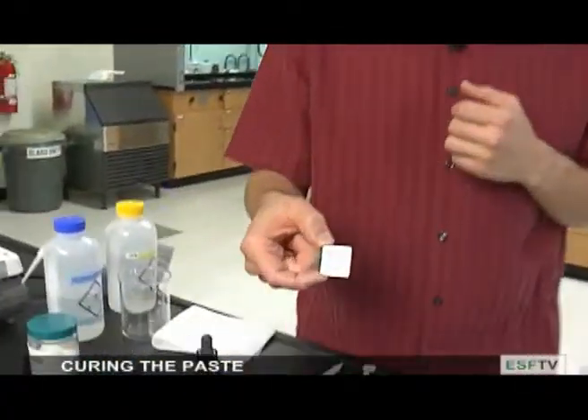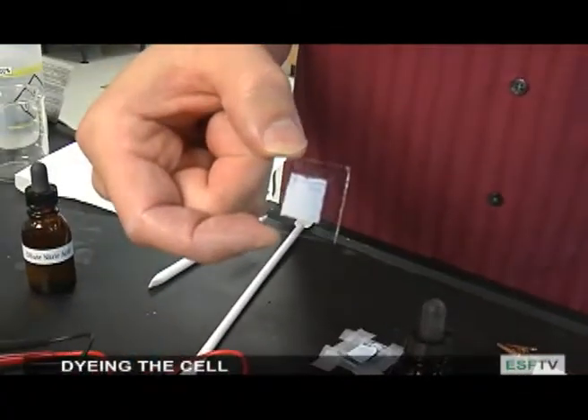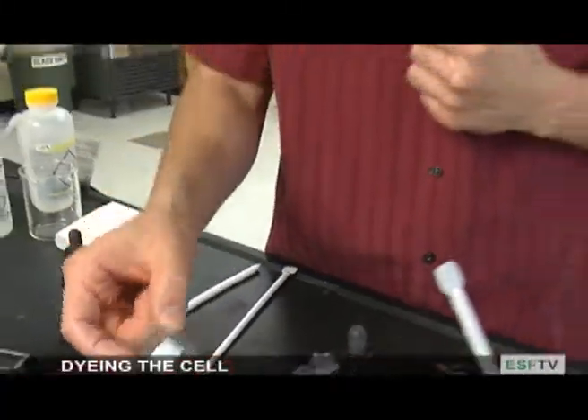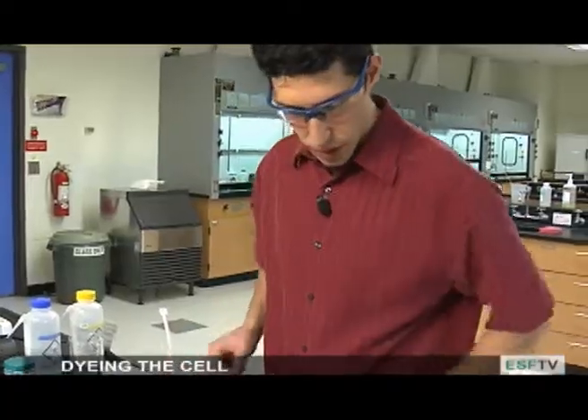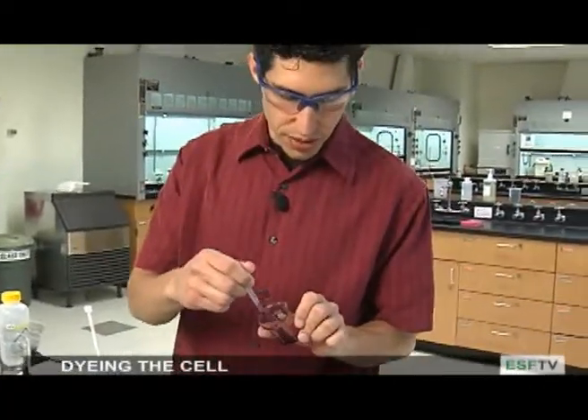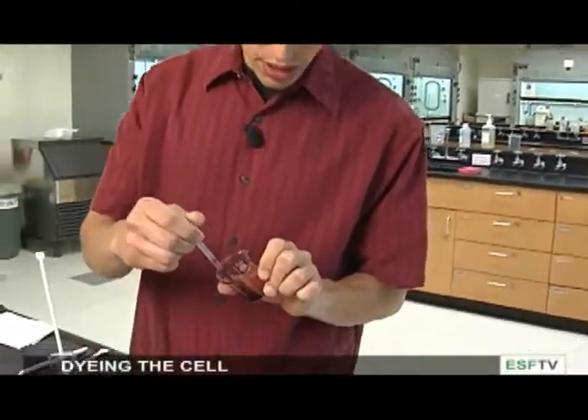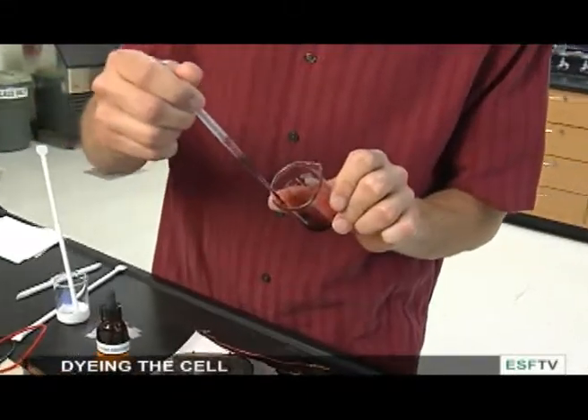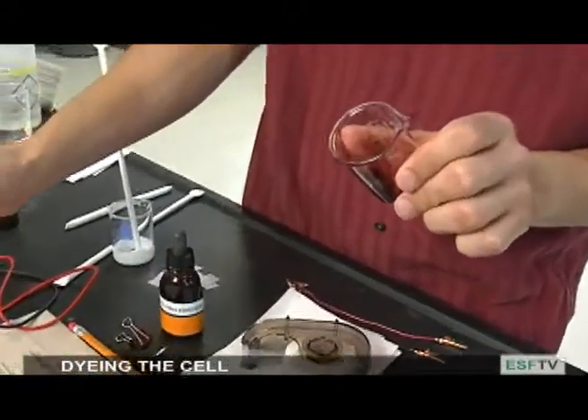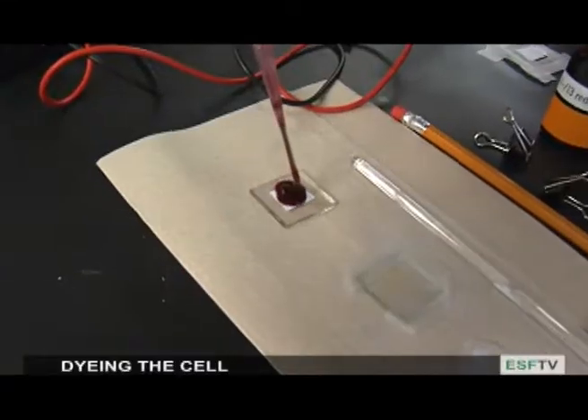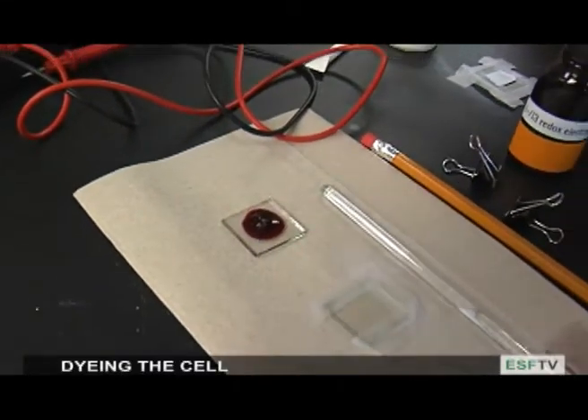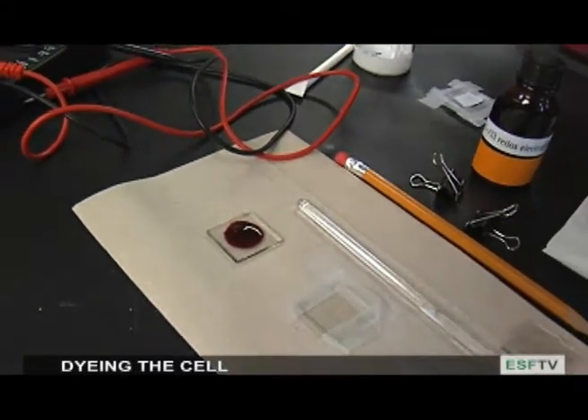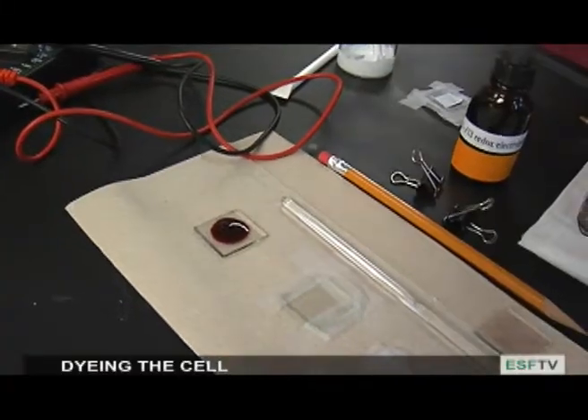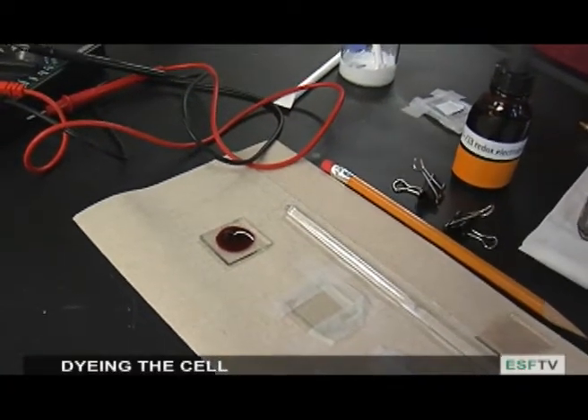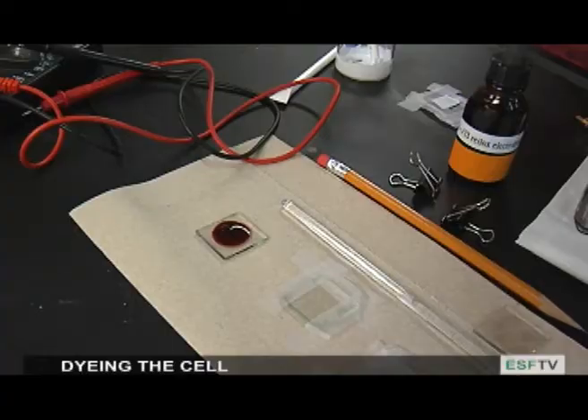At this stage, we're ready to dye the cell, so it can actually absorb sunlight. To dye the cell, we're going to use blackberry juice today. I've extracted some blackberry juice, and all we need is a small amount of the juice to place right on top of the cell. As we place it onto the cell, the juice will get absorbed onto the surface of the titanium dioxide, forming a nice purple compound. This should take about 5 or 10 minutes for complete absorption.